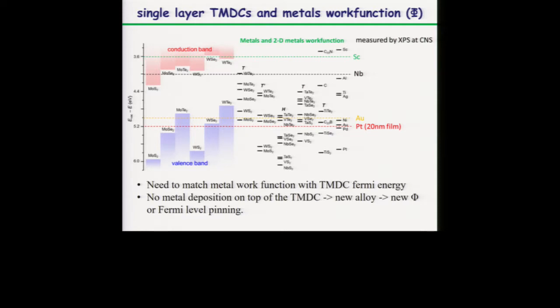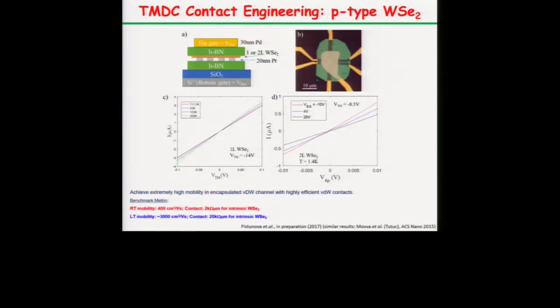Scandium also works well for MoS2, but it has a problem. All the low work function metals tend to oxidize very easily, compared to the noble metals, which don't oxidize, or if they oxidize, they form a metallic oxide. All right. So as I say, we lay down a TMDC on top of these pre-patterned electrodes, Pt in this case, and we can get ohmic contact even down to single-layer tungsten selenide at low temperature. This is around 1.5 Kelvin, and we also tested it at helium-3 temperature. So we can make ohmic contacts down to these low temperatures.